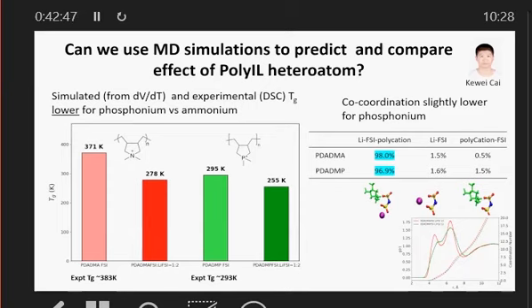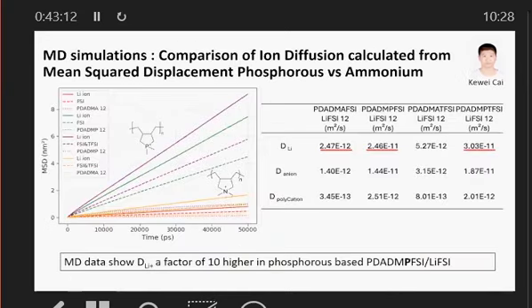We do see from the, and I won't spend much time on this, we're still trying to analyze this data in more detail, but we do see from the radial distribution function, the coordination of the P-FSI or the N-FSI is a bit different. The green is the phosphorus and the red is the ammonium. So there are some subtle differences in the coordination, but we're still to try and understand exactly what's going on here. But it is promising to see that we can model the system and we determine the diffusion coefficient.